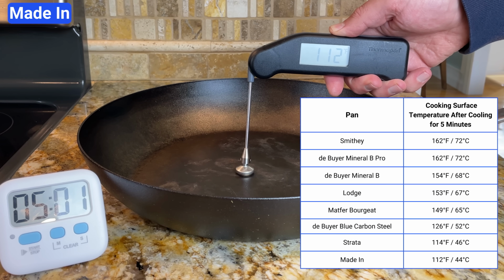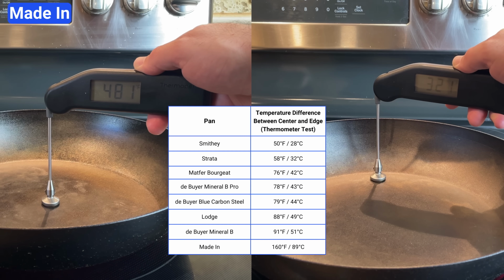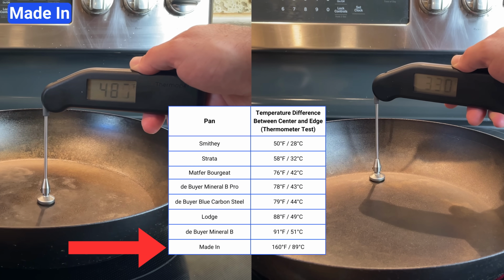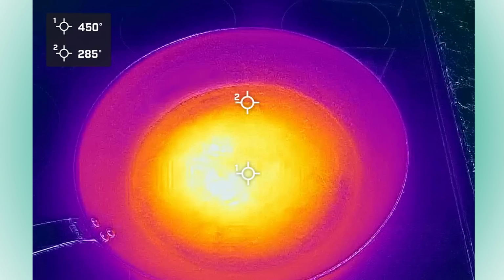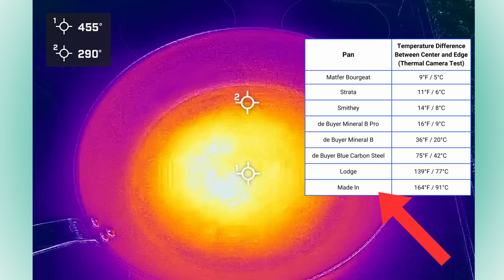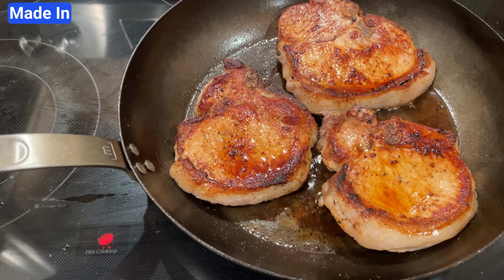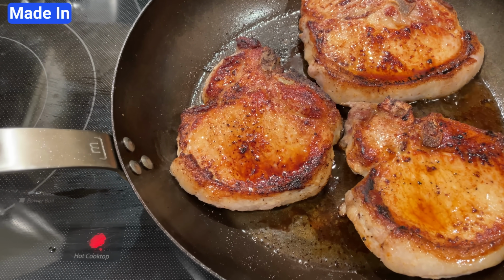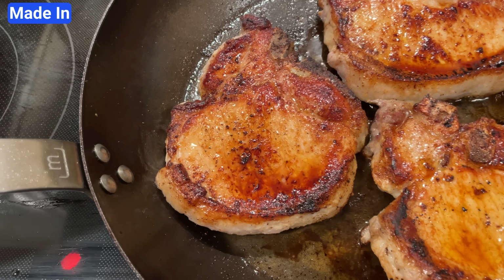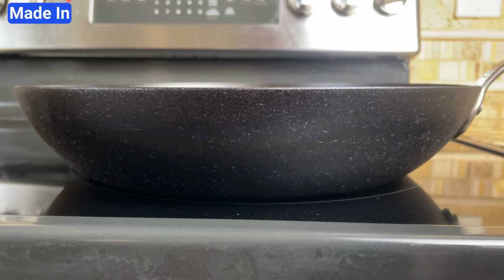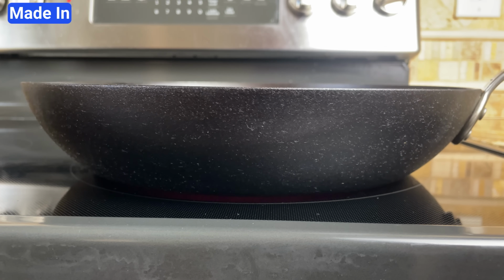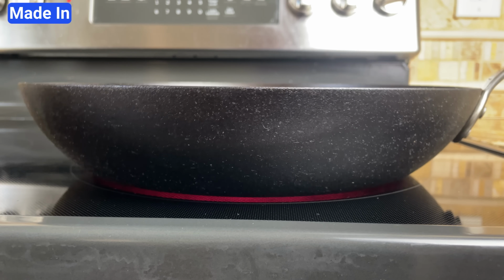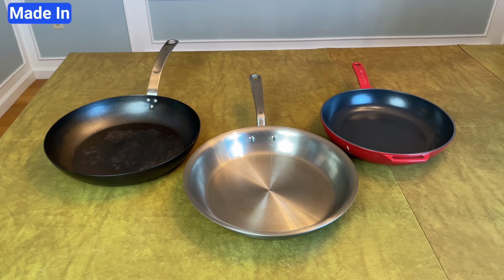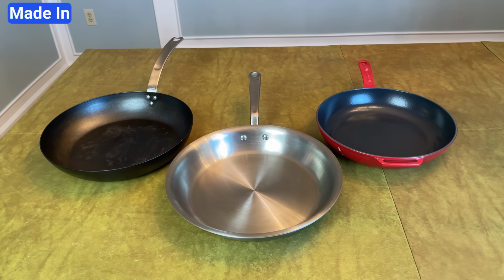Unfortunately, this pan performed the worst in my heat retention test, and in my heat conduction test, the difference in temperature between the center of the pan and the edge was by far the largest. When I tested it a second time with the thermal camera, it still came in last place. This poor performance is likely because it's the only pan that noticeably warped during testing. After months of cooking, it doesn't sit flat on the cooktop, so it's not making full contact with the heating surface. I've used several other made-in carbon steel pans, and this is the first time I've seen this issue.